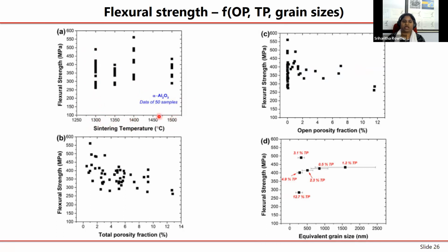So if you plot it as a function of sintering temperature, you don't see any trend. However, if you plot the flexure strength as a function of total porosity fraction, there seems to be some trend. That means your flexure strength is decreasing with increase in porosity. That sort of makes sense. Then what if you plot as a function of open porosity fraction? Then this is the sort of diagram you get.